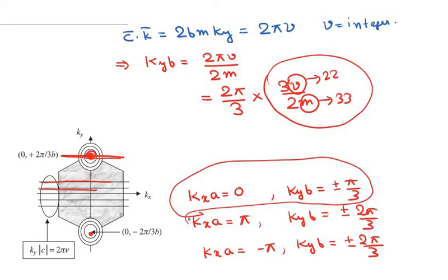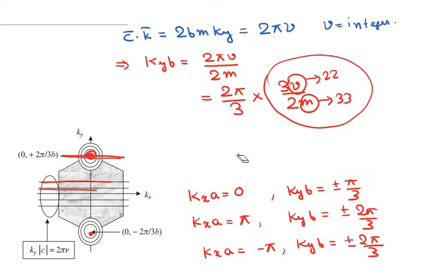Okay, that condition can also be satisfied so that this carbon nanotube is metallic. So this is how you check how to make a carbon nanotube with metallic property. And if you also want a carbon nanotube with semiconducting property, which has a band gap, then you can make one by making this m a non-integer multiple of 3.